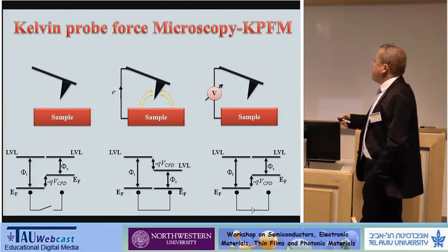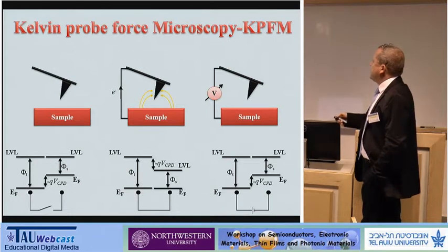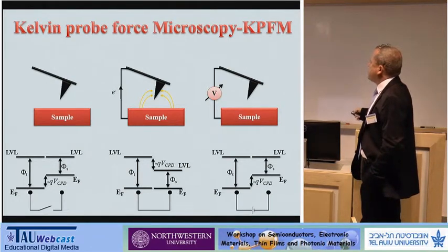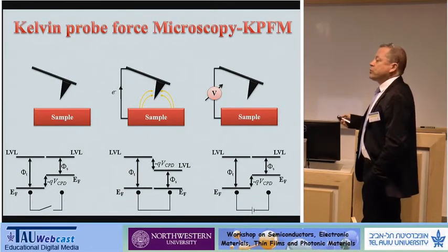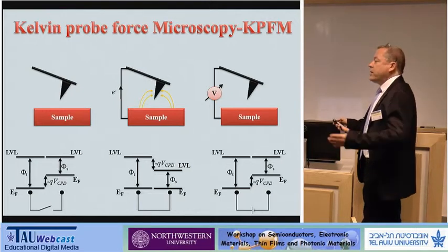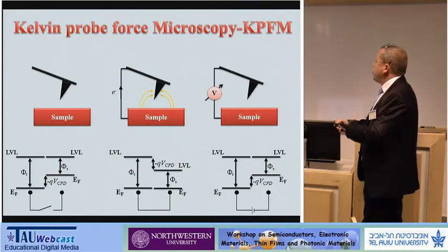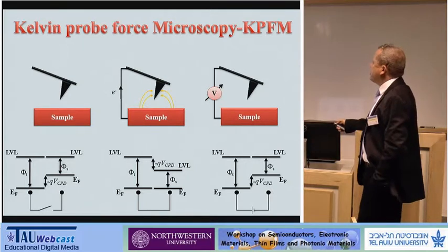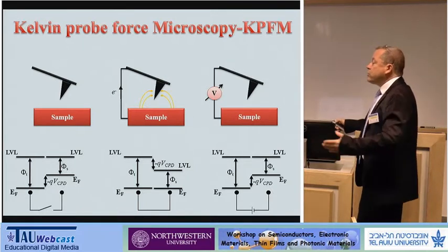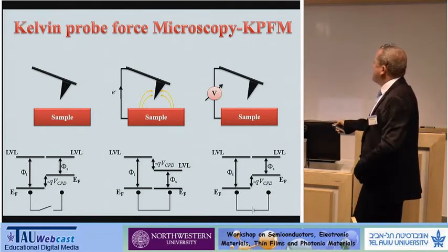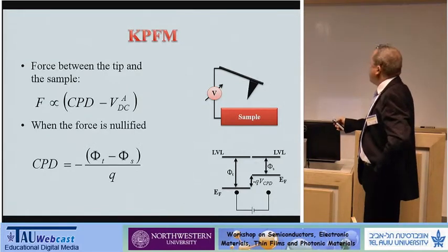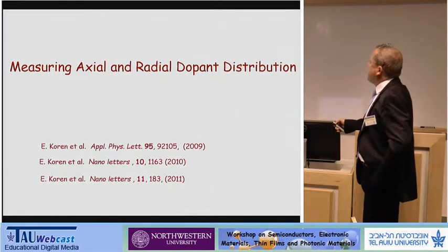A slight disadvantage relative to STM that David described earlier and that Mark Hersam knows very well is the lateral resolution. The lateral resolution, depending on whether you're working in ultra-high vacuum or in nitrogen like we work, is around 20 nanometers, a few nanometers in ultra-high vacuum. But for our study, this is not a big issue.